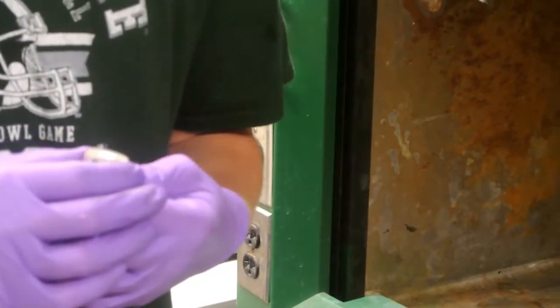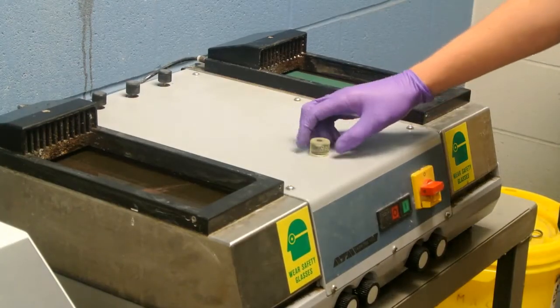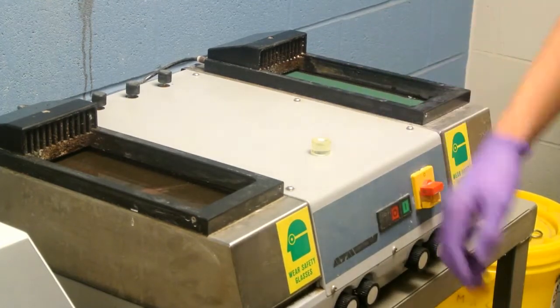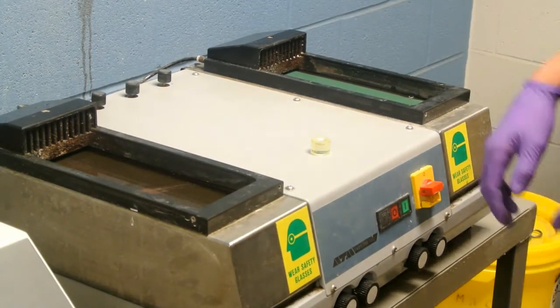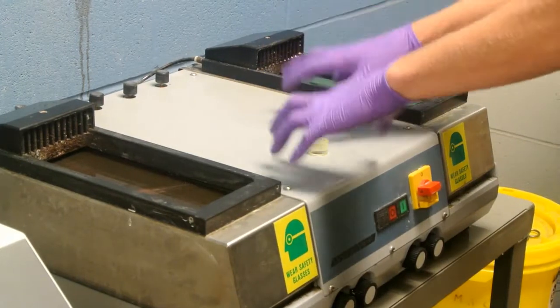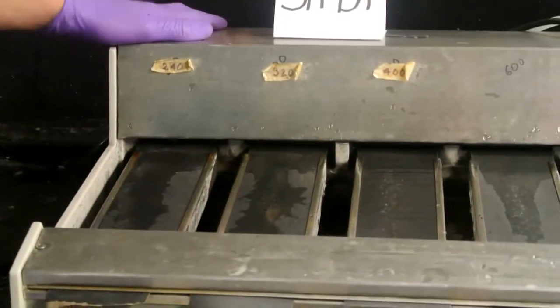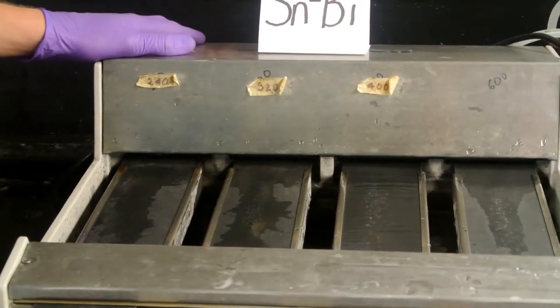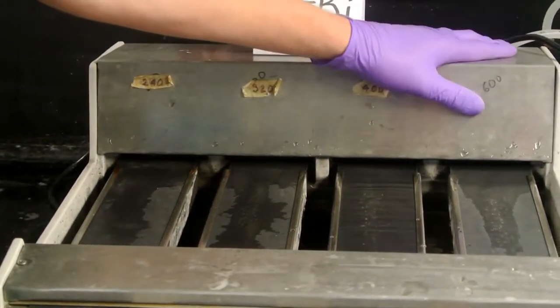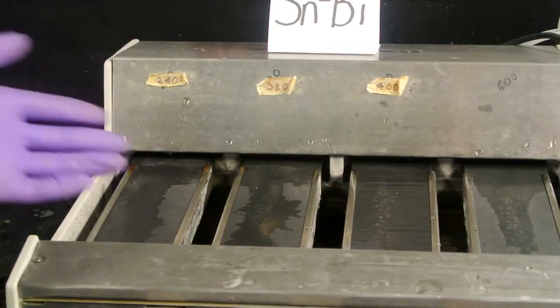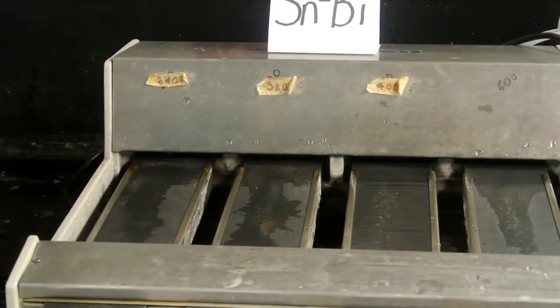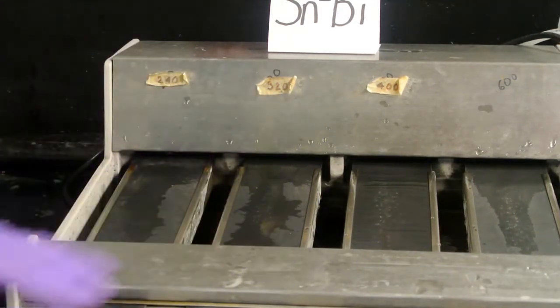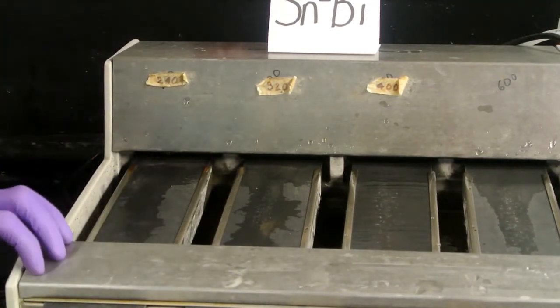the microscopes. So far we've polished this sample up to 600 grit on the sandpaper. Stage 1 was using this rough grinder, and it goes up to 120 grit. Stage 2 was with the 240, and it ended at stage 5 being 600. Obviously going through 320 and 400 grit, polishing it, cleaning it, and rotating it each time. Now we're going to do 600 grit on the polishing.